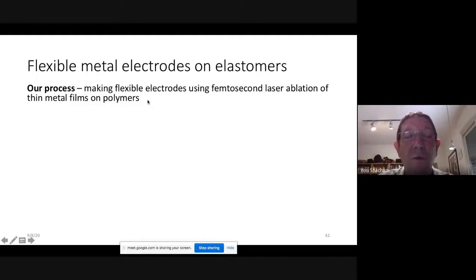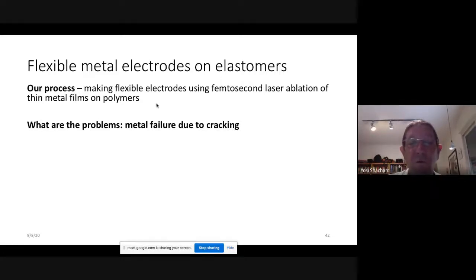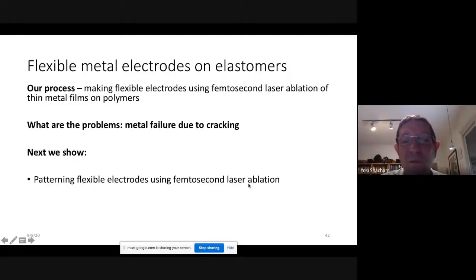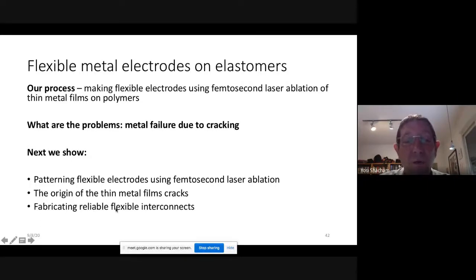So our process, which we developed at Tel Aviv University in collaboration with the University of Milano, is flexible electrodes using femtosecond laser ablation on thin metal films and polymers. I'm switching now from the large overview of the field. Until now I gave 35 minutes of review of the field of flexible electrodes and described all the materials. In the next 20 minutes, I'm going to talk about what we do and how we solve the problems. One of the biggest problems that everybody faces is metal failure due to cracking. Next we show patterning of flexible electrodes using femtosecond laser ablation and the origin of the crack. In order to solve the cracking, I will explain why there is cracking and how to avoid it, how to make reliable sensors.